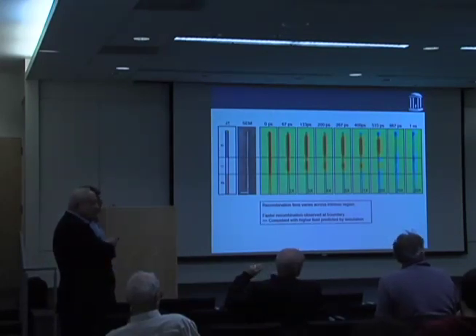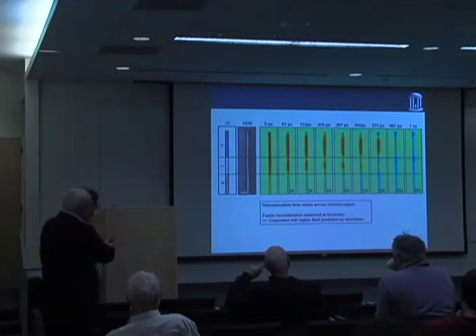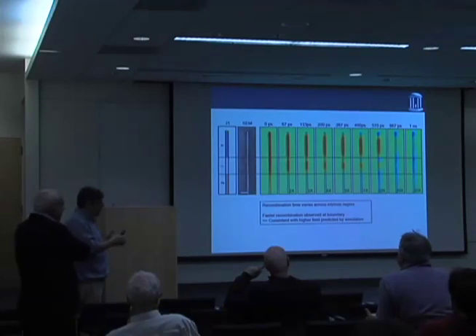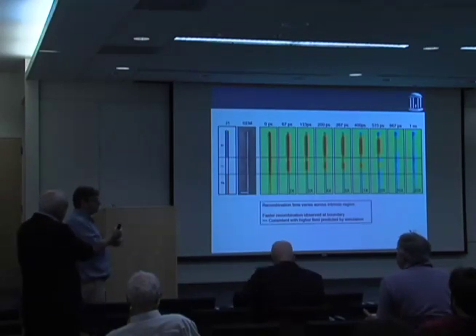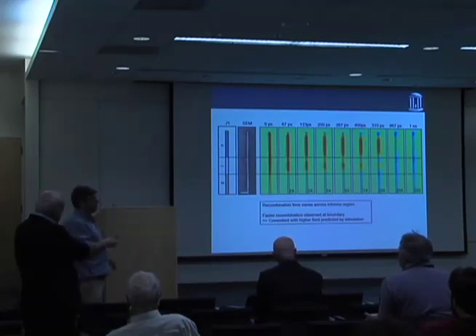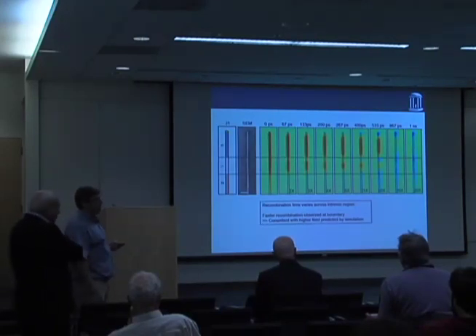Yeah, so that would be really cool. We've gotten a lot of samples from Jim where something happens during the growth process and it becomes unstable, and all of a sudden it starts growing in a different direction. So far in Jim's group, it's been more of an uncontrolled process, but there are people that are really good at it, and there are things in the literature where it looks like a zigzag structure. Those would be some really interesting things to look at, to see how the carriers behave in and through those regions.